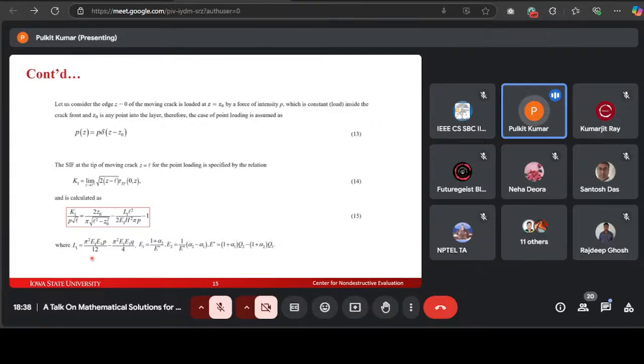Now let us consider the edge y equals z equals 0 of the moving crack, loaded at z equals z0 by a force of intensity P, which is constant inside the crack front, where z0 is any point in the layer. Therefore, I am assuming the case of point loading as P of z equals P times the Dirac delta function of z minus z0. This is considered because it is mathematically convenient for solving the integral equations.